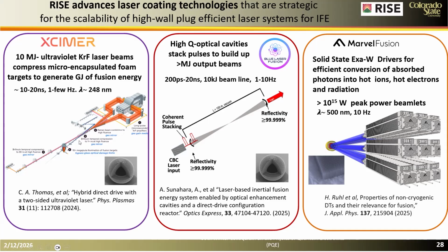In this approach, optics are only needed on the beam detectors, and we need to direct the beams into gas cells, because the pulse compression and pulse beam combining will be done using nonlinear optics. This is the concept that Excimer Energy is using. The concept that Blue Laser Fusion is proposing for its driver is a cavity like the LIGO cavity, an optical enhancement cavity. You need mirrors with 99.999% reflectivities, extremely low absorption loss, and very high laser damage threshold. Marvel Fusion is developing high peak power lasers,